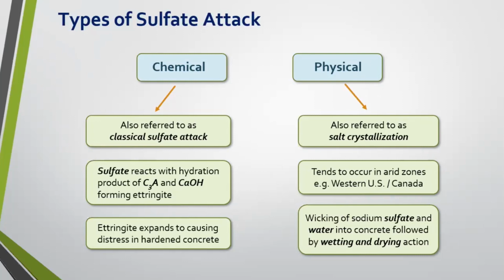On the physical side, physical sulfate attack, this is also sometimes referred to as salt crystallization. Now, this tends to happen in arid zones like the Western US and Canada, basically areas with very little rainfall. And so your concrete through these dry periods will become very thirsty, so to speak. And you get this wicking action where sodium sulfates are drawn in from groundwater or soils or multiple sources. And this is followed by wetting and drying. And as this happens, you've got these crystals forming, and then they break back down into solution. They form again, reform. And same thing, you're getting expansion, you're getting stresses within the concrete matrix. And this can actually happen very quickly. We'll look at some pictures here in a minute that differentiate these.